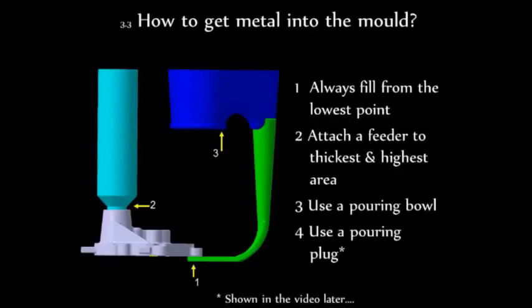The reason we do it like this is if you pour it in the top, basically the metal splats and kind of falls down and bounces off other bits. And if you've ever made hot chocolate, you know, if you let it sit there for a minute, you'll get this horrible skin on the top and you have to throw it off. Basically, when aluminium is liquid, it's forming a skin on it. And every time a bit of it is exposed to the atmosphere, it forms a skin, which is basically a skin of a bit of rubbish, it's not metal, it's oxide. So every time it splashes, lots of little bobbles are getting covered in air and they're forming a skin on. So basically if you pour your metal in straight from the top, you're guaranteed to have complete rubbish parts that are full of bits of air and oxide and all sorts of stuff.